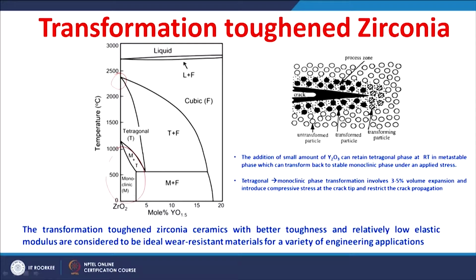So, this metastable phase can again retransform into monoclinic under an application of external stress. This tetragonal to monoclinic phase transformation involves a volume expansion of around 3 to 5%. Because of this volume expansion and the strain, that introduces compressive stresses at the crack tip. You can see here a schematic showing the tetragonal phase transforming to monoclinic, and these are the transformed particles of monoclinic. In the vicinity of this crack there is a transformed zone of monoclinic. Because of this tetragonal to monoclinic transformation, a compressive stress is generated on the crack.